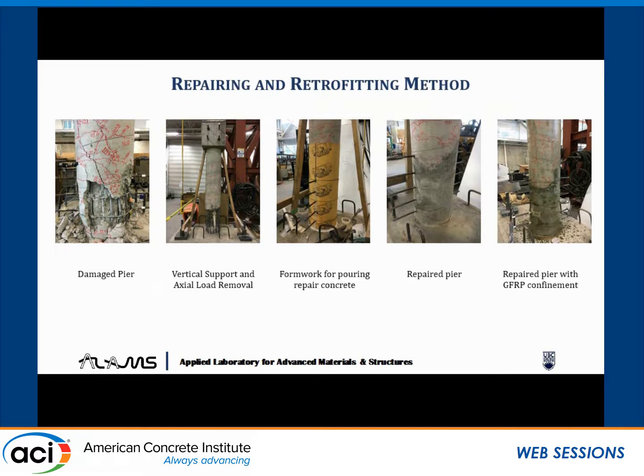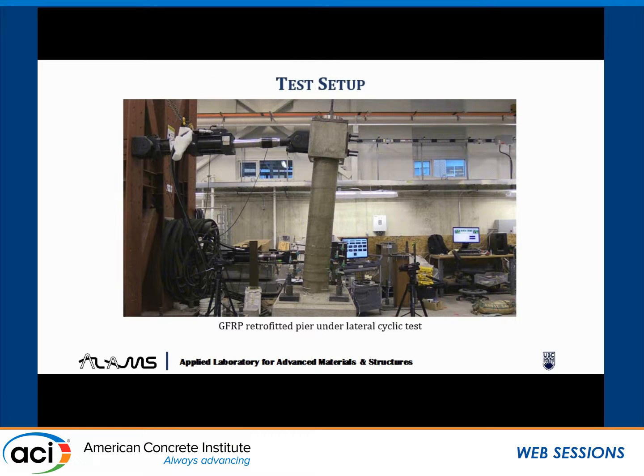And here in this particular case, I should mention that we had 3 specimens. One was a control, and we tested it, and then we damaged the column, and then we repaired it with GFRP. And we had another control column. So before testing, we retrofitted it with GFRP, with the same materials, same number of layers of GFRP.